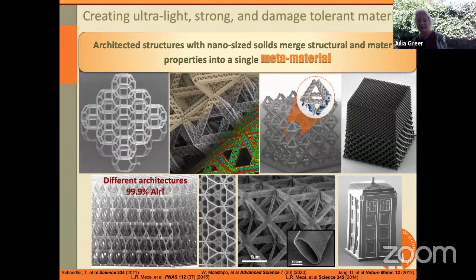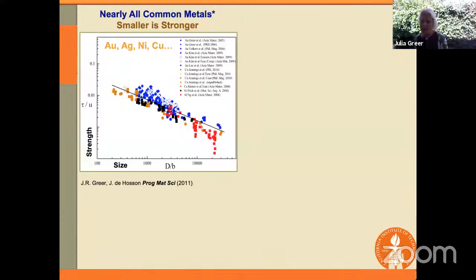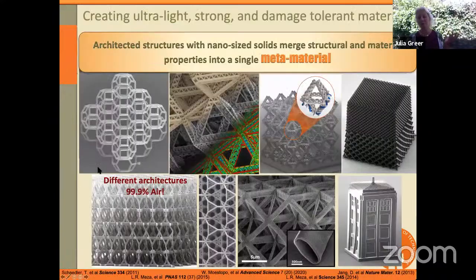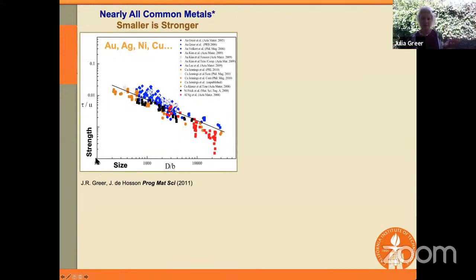At these length scales, at the nano length scales, these properties are no longer independent of one another. Now, I demonstrated to you that these are very lightweight, but I have yet to show you why they're high strength. And so here's an example of a so-called size effect. If we plot strength, normalized by the shear modulus, as a function of size for a variety of common metals, these could be things like gold and silver and nickel and copper.